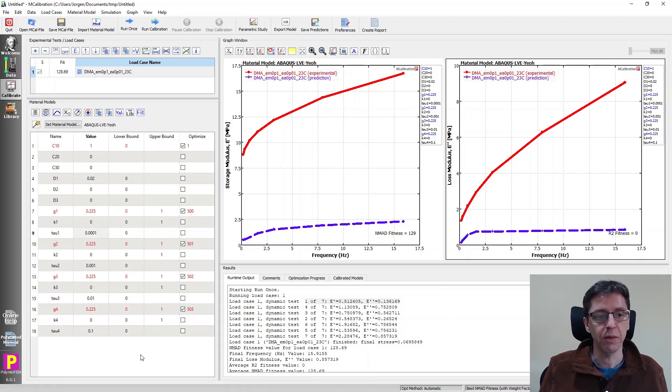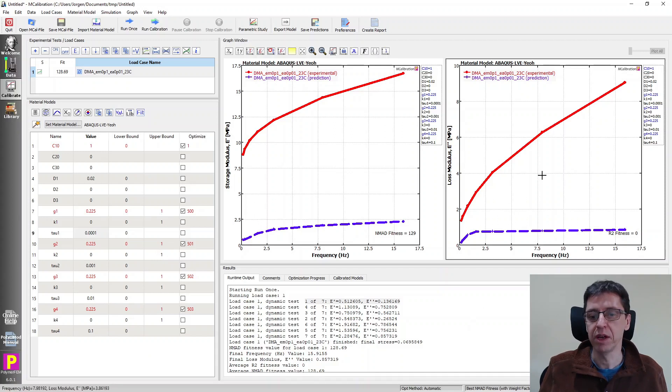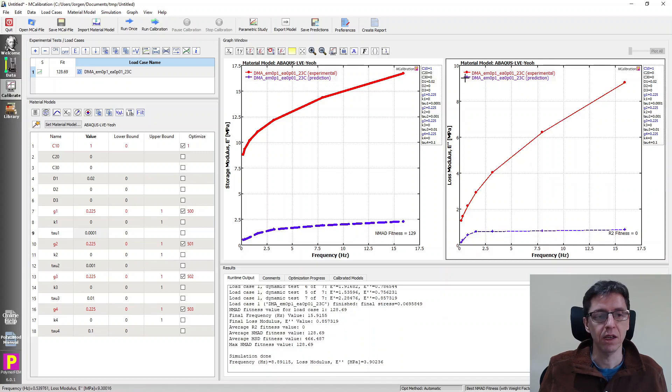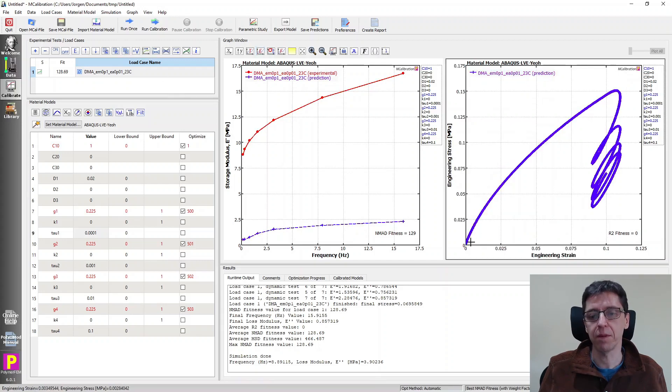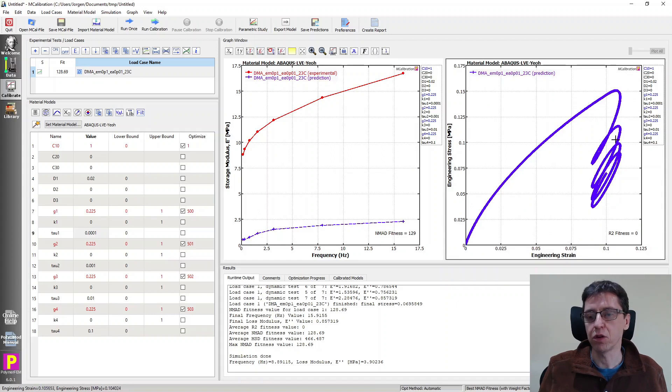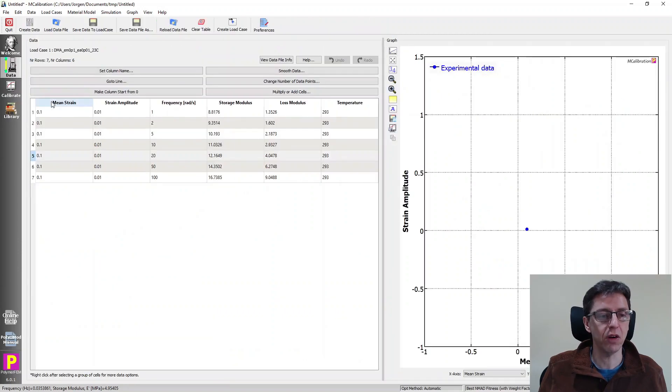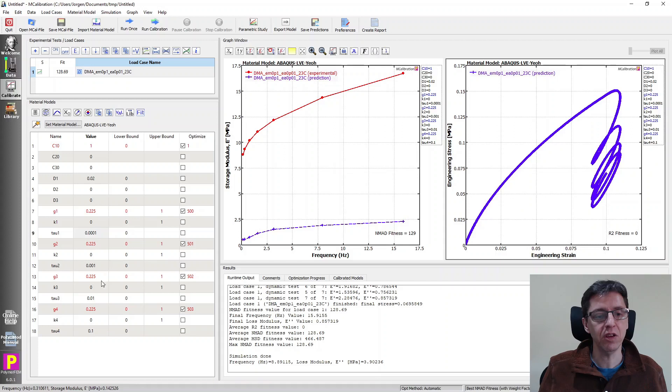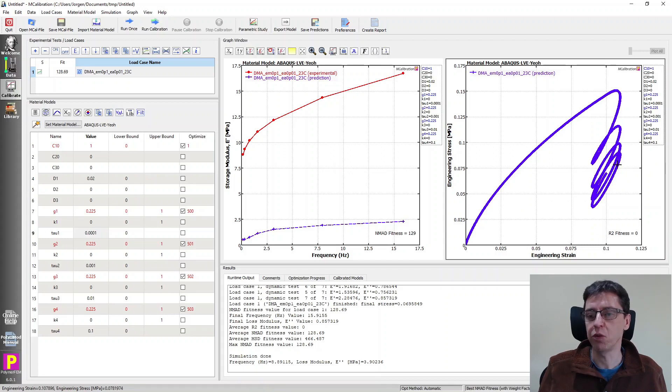Before we try to optimize the parameters, it's good to plot some other things here to kind of explain this a little bit more. So in my figure to the right here, I'm going to plot engineering stress, engineering strain in this case. So I'm going to click on this E button here. And what we see is that it plots the predicted stress strain curve for the last cycle of the last, for the last of these rows. There's seven rows of data here and it takes the last one and plots this here. So what we see is that with these parameters that we have right now, each cycle the stress keeps going down due to viscous relaxation. So we don't actually have an equilibrium state yet.